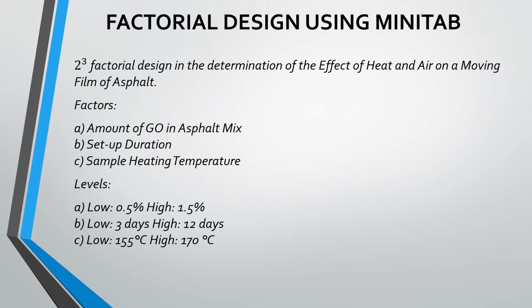For setup duration, the low will be 3 days and the high will be 12 days. And for the sample heating temperature, we'll have the low at 155 degrees Celsius and the high at 170 degrees Celsius.